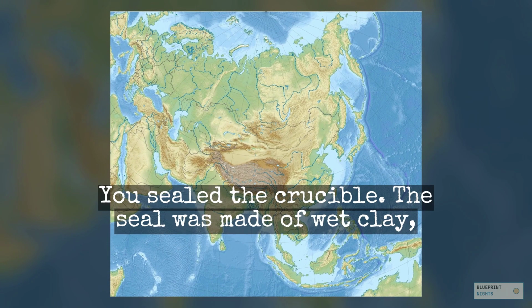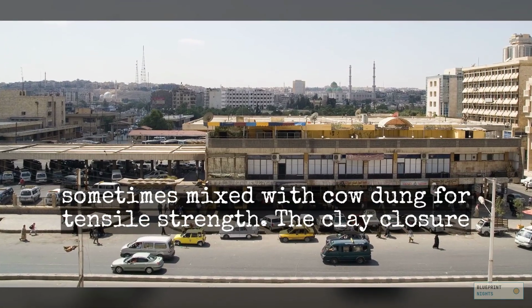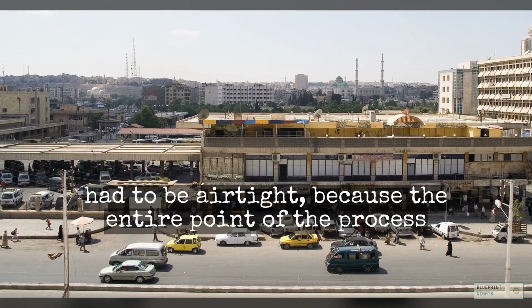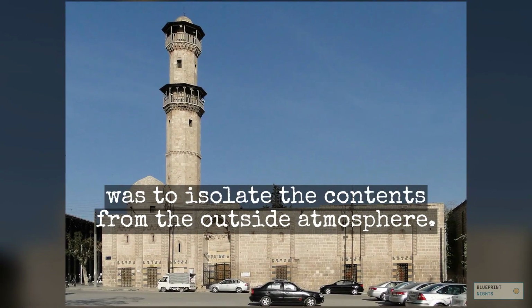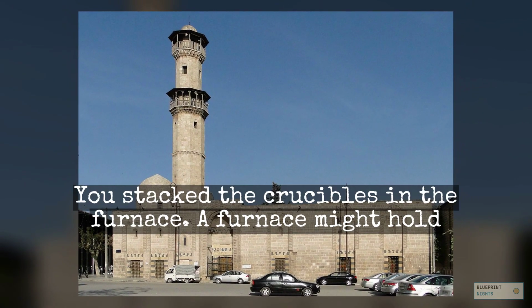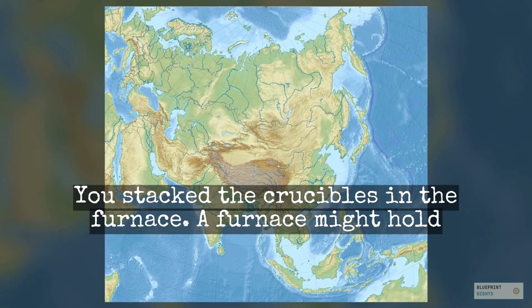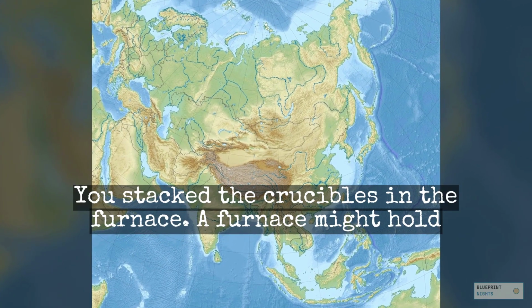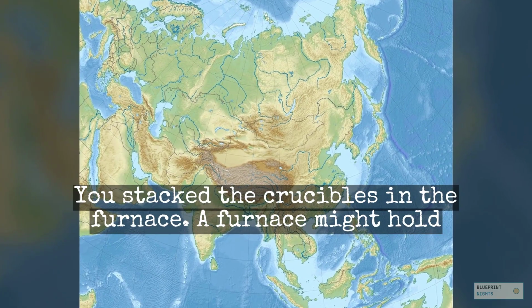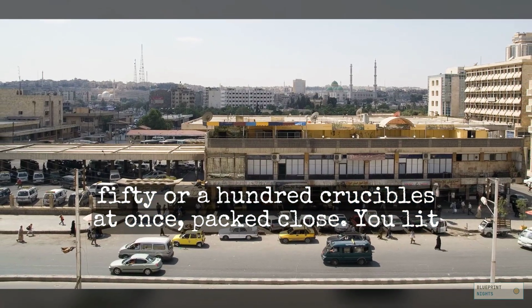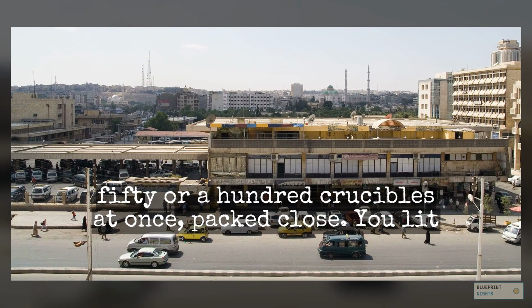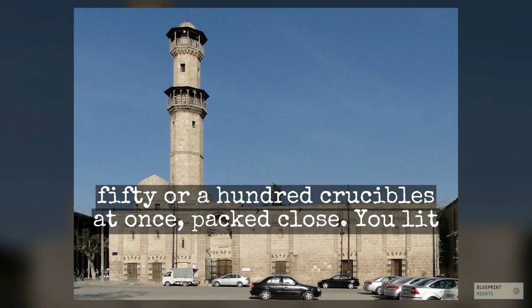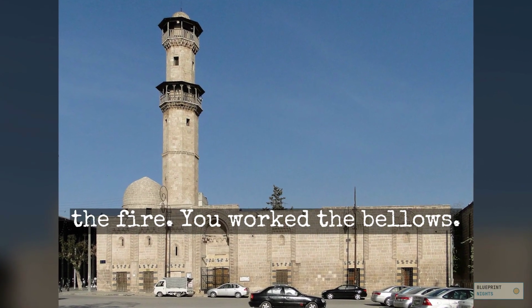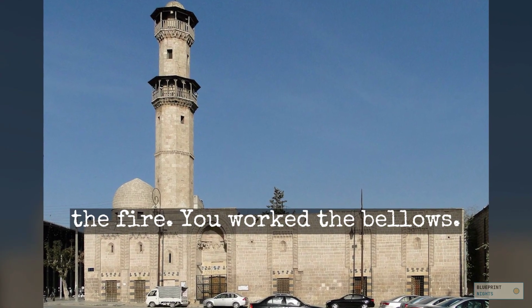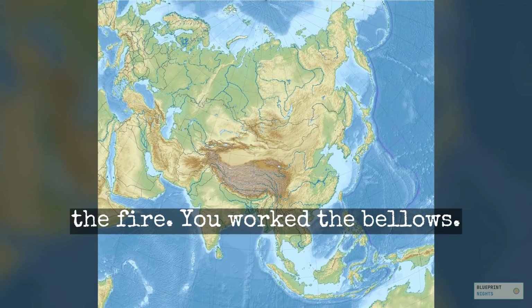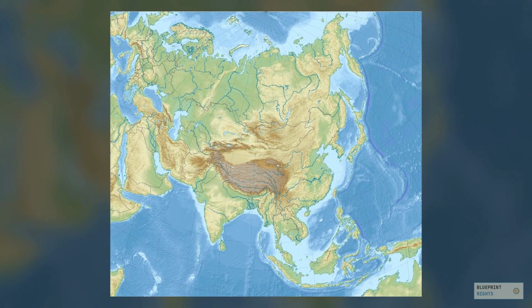You sealed the crucible. The seal was made of wet clay, sometimes mixed with cow dung for tensile strength. The clay closure had to be airtight because the entire point of the process was to isolate the contents from the outside atmosphere. You stacked the crucibles in the furnace. A furnace might hold 50 or 100 crucibles at once, packed close. You lit the fire. And then you waited.